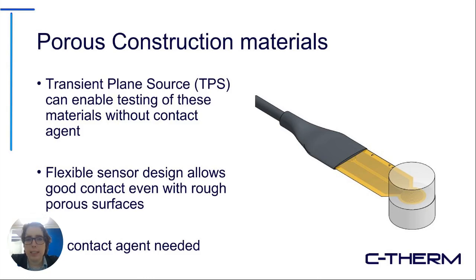So when you're looking at construction materials, many of them are highly porous and hygroscopic. So if you're using a test method that requires a contact agent, it can be difficult to test them with that kind of a test method. Like, for example, a heat flow meter type of method would require a contact agent as one example. So the fact that the flex method does not require a contact agent becomes pretty attractive in these kinds of cases because you don't have to worry about the sample absorbing the contact agent and increasing its effective thermal conductivity as a result.